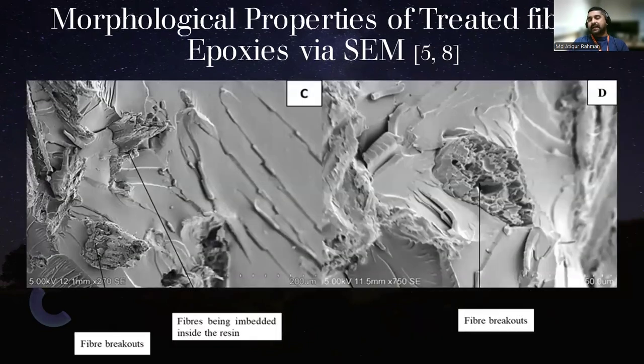Let's see the treated fiber epoxy under SEM. You can see that all the fiber is embedded inside the resin very rigidly. Apart from that, after the fracture, we can see that rather than the fiber pull out earlier, it was fiber breakage. That is the pure indication of good adhesion property, and that affects its mechanical and thermal properties.